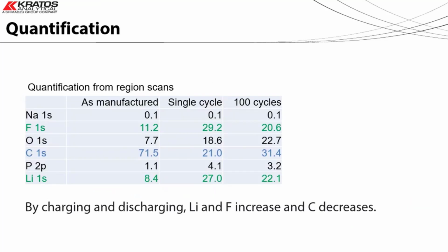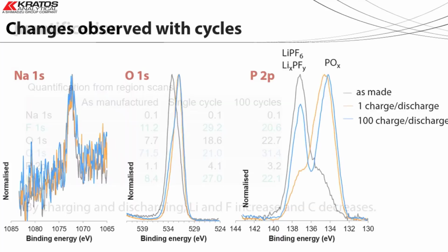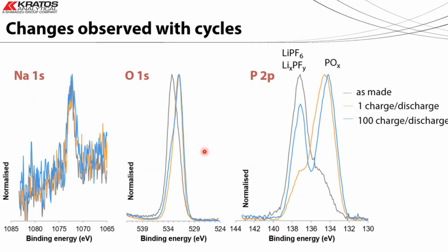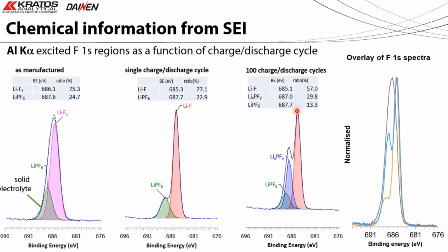So the quantification, again using the aluminium, shows that we've got an increase in the fluorine signal and the lithium, and a decrease in the carbon signal. So we can make sense of that by looking at the narrow region scans. We can see that there's some interesting chemical shifts going on as we increase the number of charge-discharge cycles. Some nice changes particularly in the phosphorus 2p region. These are mirrored also in the chemistry that we see in the lithium region.